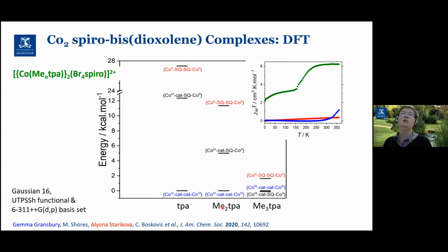When we go to the dimethyl TPA, so now we're putting methyls around that TPA, we're starting to stabilize the cobalt-2 containing forms. They're coming down in energy. And we can see now that that mixed valent state is actually low enough in energy that we can just start to see that onset of that first step of the VT complex. So that's the data points there in blue.